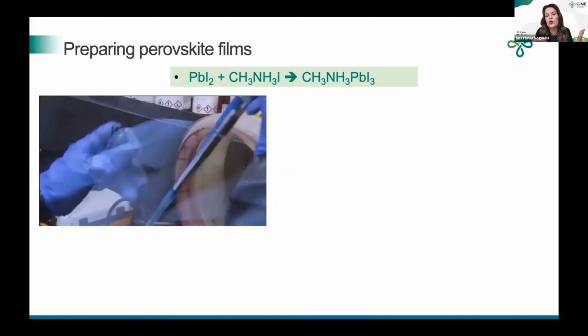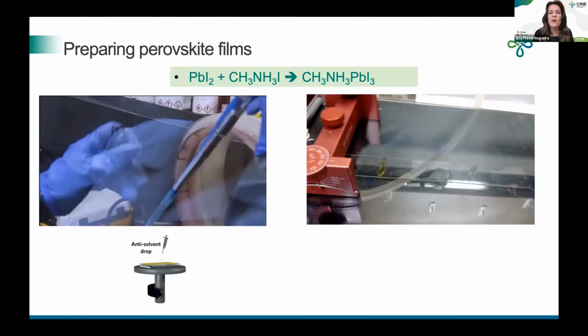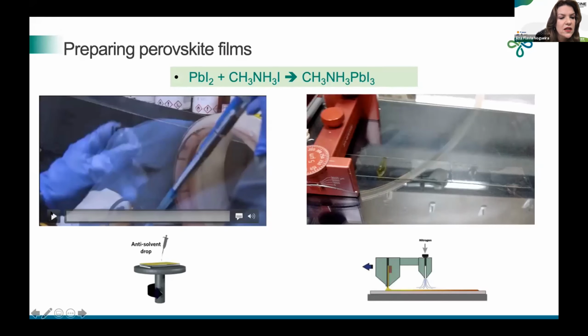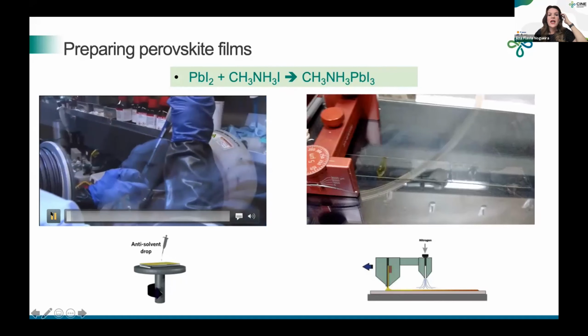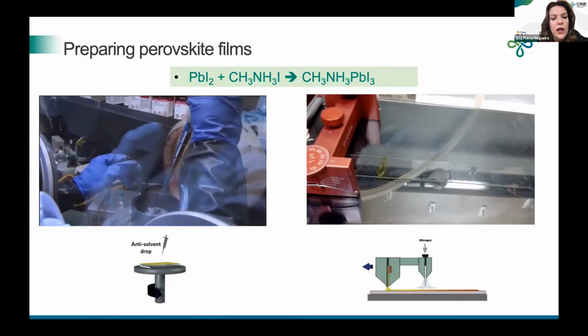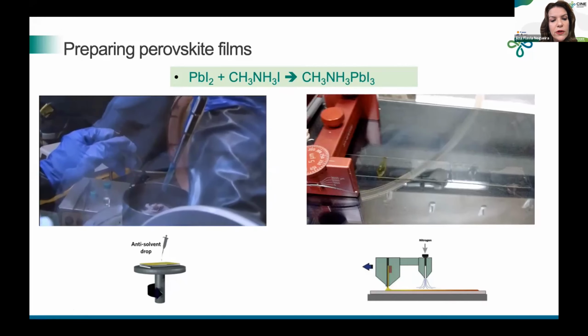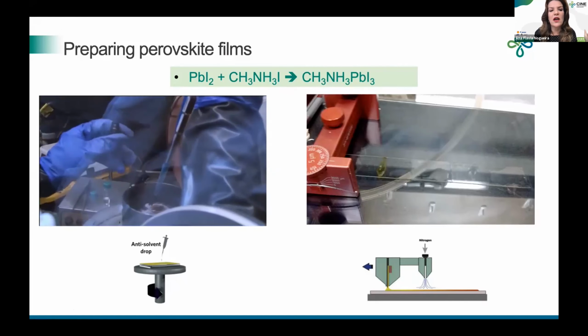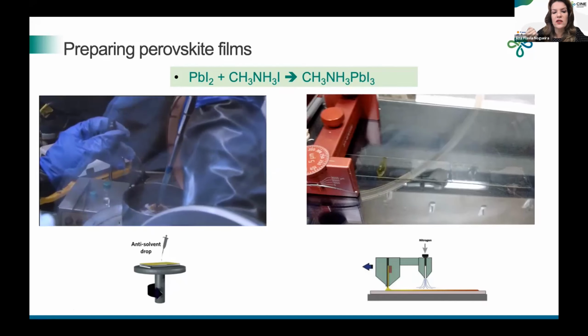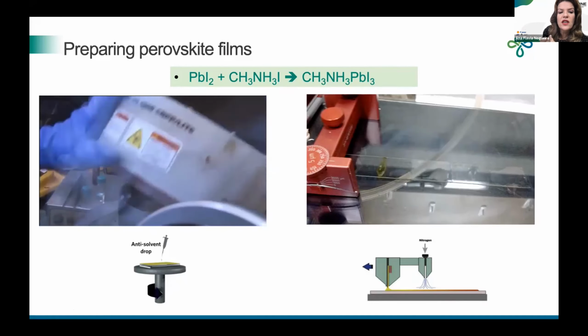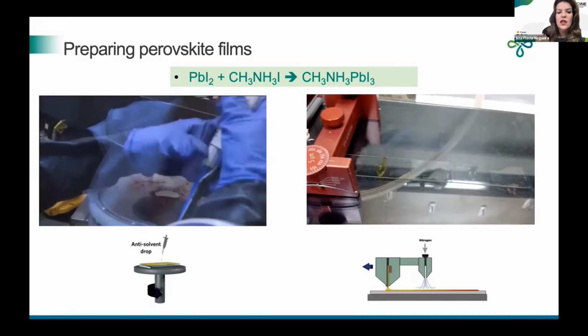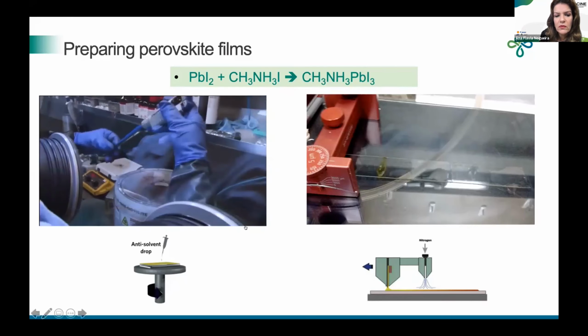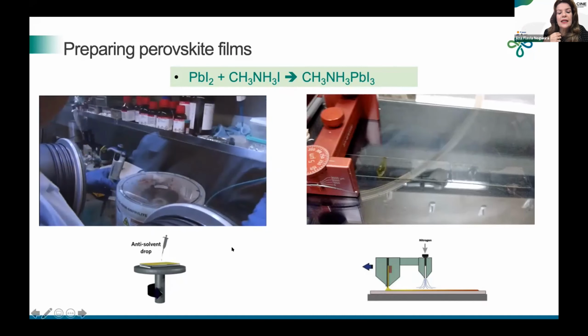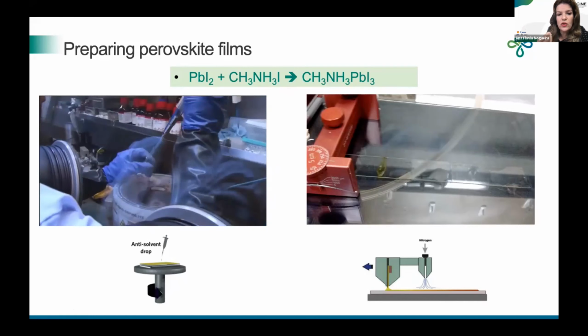It's the same we are doing now in our lab. The first most used method to prepare the perovskite is the anti-solvent. I'm going to play this video here so that you can see. You spread the precursor solution in a spin coater. Just before the end of the spin coating, you drop the anti-solvent. Pay attention here: as soon as you drop this anti-solvent, you are going to see a change in the film and the film color, where you see the actual formation of the perovskites.